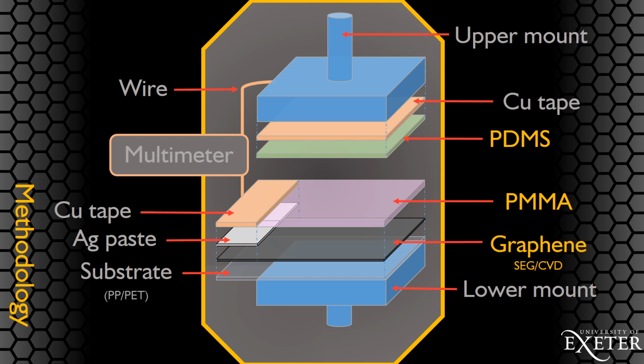This sits atop the graphene electrode obtained either from shear exfoliation or chemical vapor deposition. Their respective performances were compared to identify the more suitable process to use in this TENG. The substrate type to hold the graphene was also a variable being tested. Polypropylene fibers, PP, and polyethylene terephthalate, PET sheets were chosen for being lightweight, cheap, and demonstrated a reasonable ease to